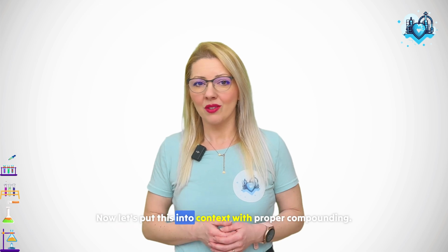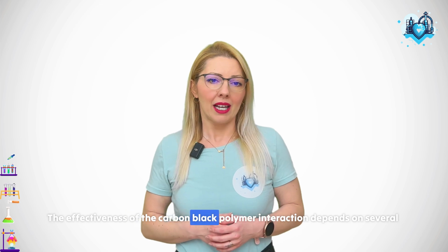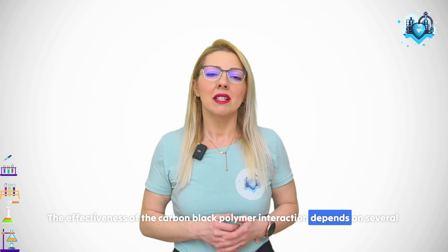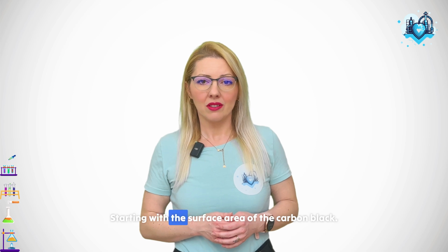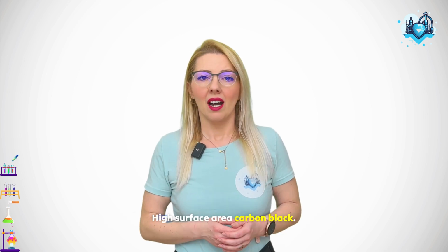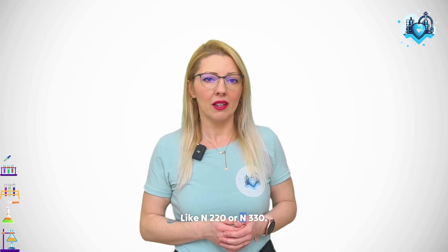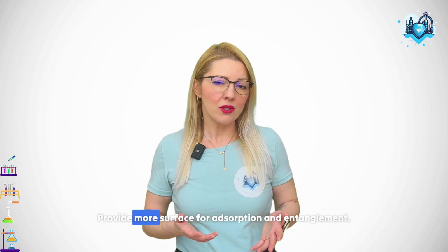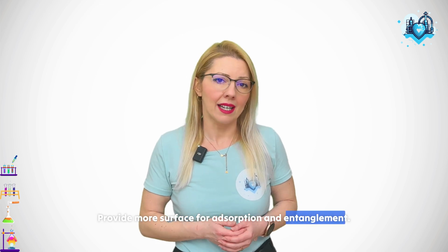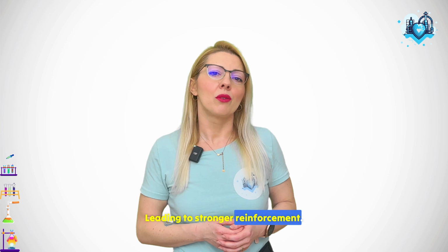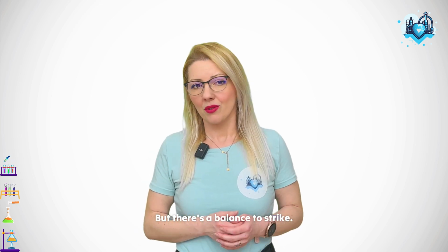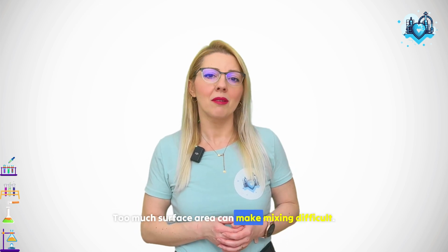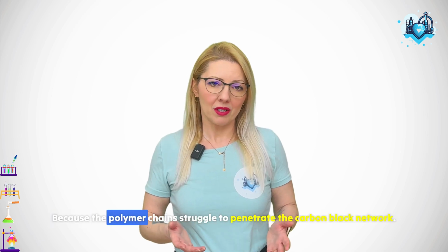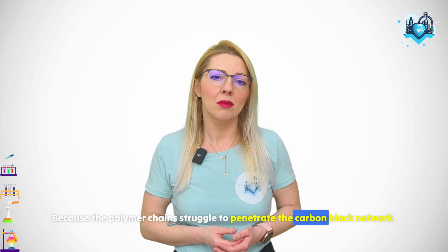Now, let's put this into context with proper compounding. The effectiveness of the carbon black polymer interaction depends on several factors, starting with the surface area of the carbon black. High surface area carbon blacks like N220 or N330 provide more surface for adsorption and entanglement, leading to stronger reinforcement. But there's a balance to strike. Too much surface area can make mixing difficult because the polymer chains struggle to penetrate the carbon black network.